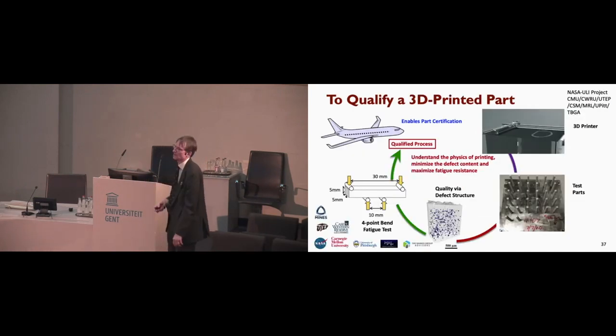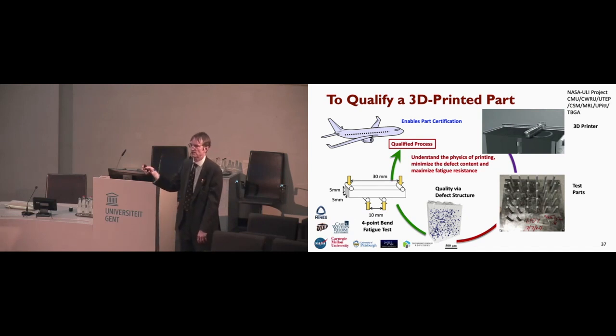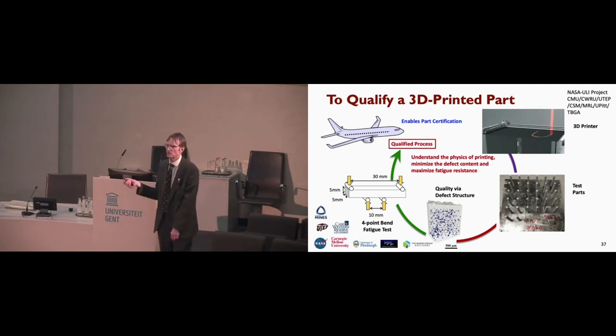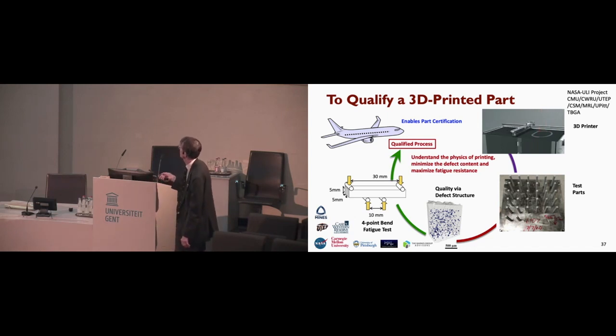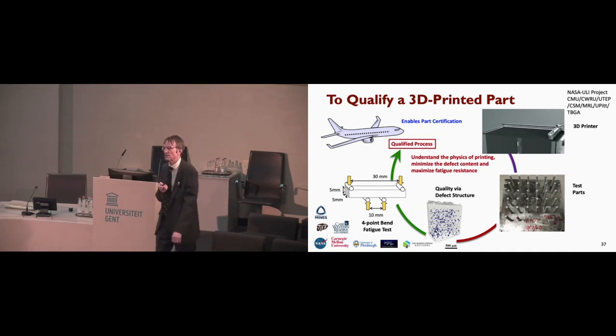So now to reconnect us to industrial application and why you might actually care about this from a practical point of view, I give you a very quick two-slide summary of a major NASA-supported project. We're very grateful to them. Multiple institutions where we are doing laser powder bed printing of Ti 6-4. We're basically just printing these fatigue bars about 5 millimeters on a side. We are, of course, characterizing the defect structures. We're doing four-point bend fatigue on them.